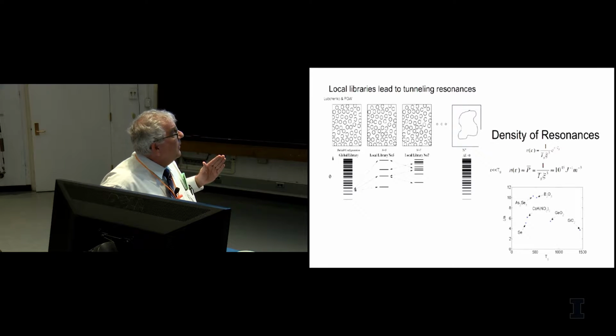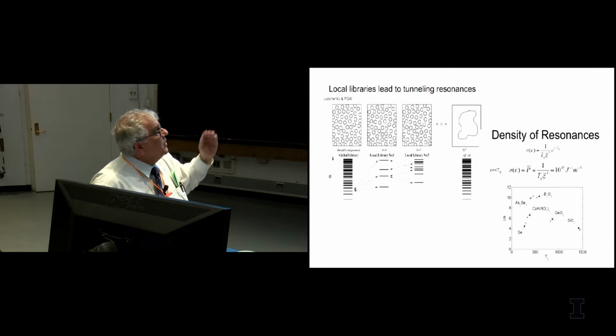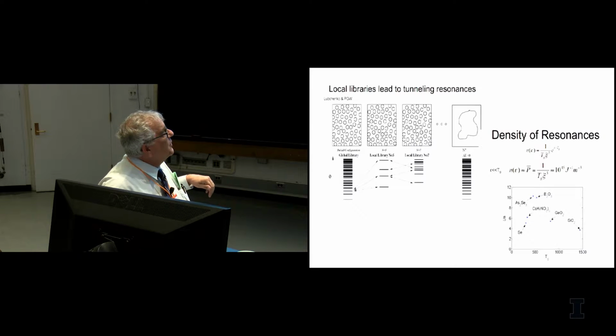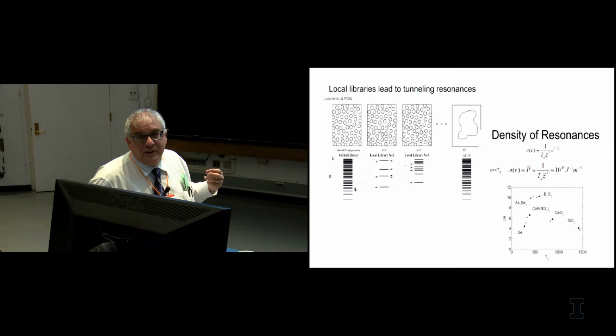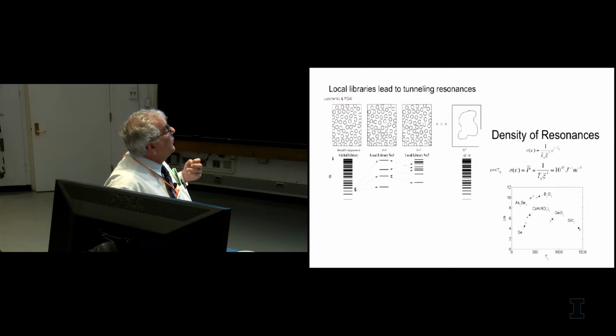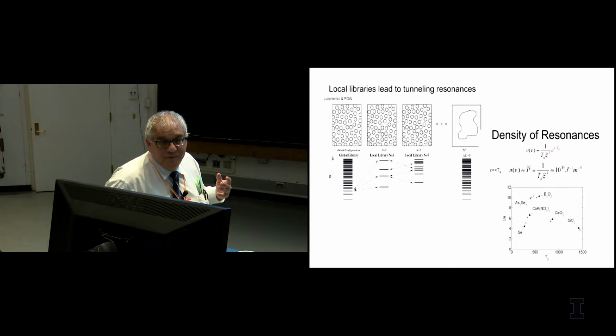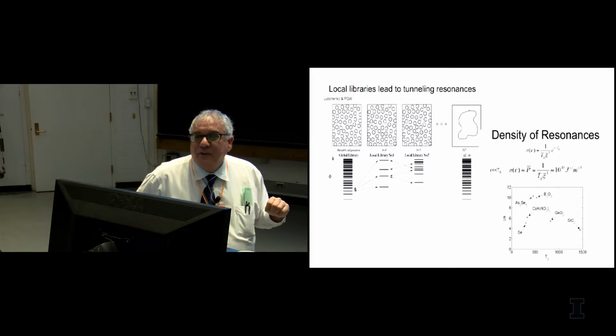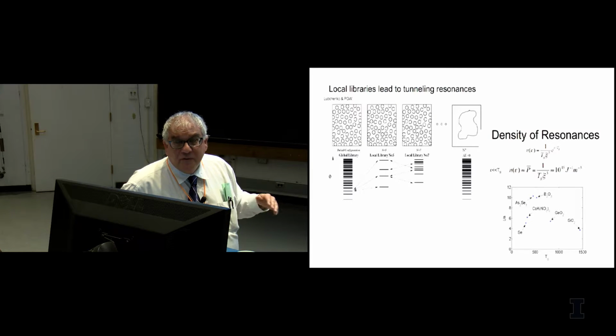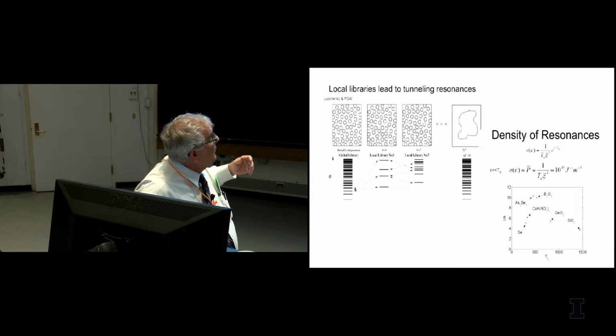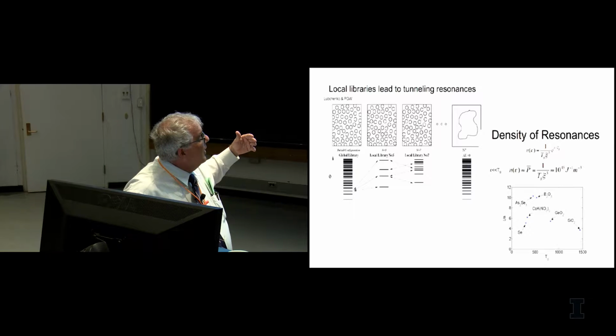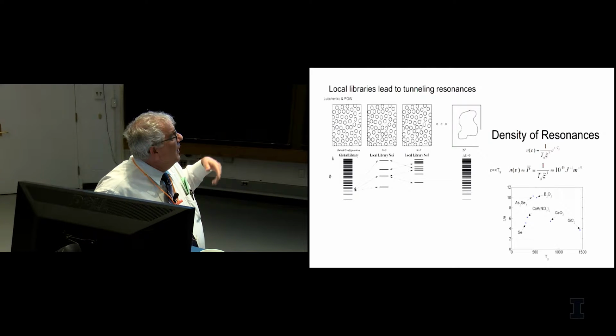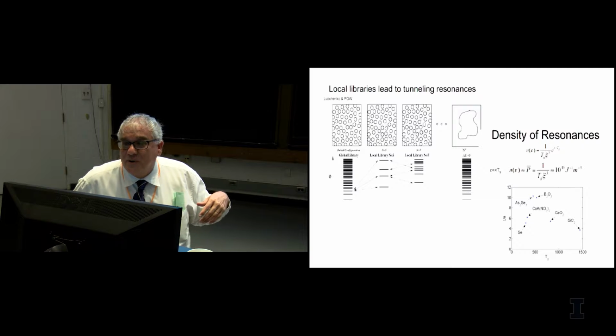the entropy variation with energy at the glass transition temperature. The energy scale is set by the glass transition temperature. And then you also have this size. So this predicts a rough number that's universal for these substances, always in the range of about a density of states of 10 to the 45 per joule per cubic meter.